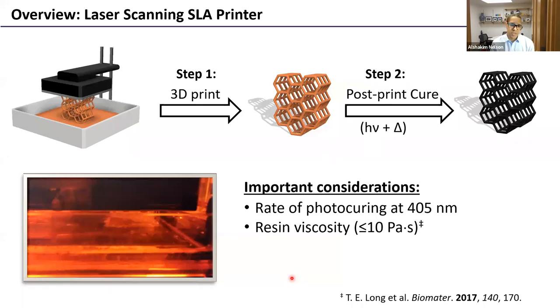And we're also using a different type of printing as well. So whereas before we were using extrusion printing, here we're using laser scanning SLA printing. And in this type of printing, what we have is a vat. And this orange material here is supposed to be the liquid resin. So it has to be liquid. The bottom of this vat is transparent. Okay? And so what we can do is use light to pattern the material through the transparent layer underneath. And then we're printing just a very thin layer, one layer at a time, until we can produce the entire printed construct. And then in a second step, we may have to cure the material to get the mechanical properties that we need.